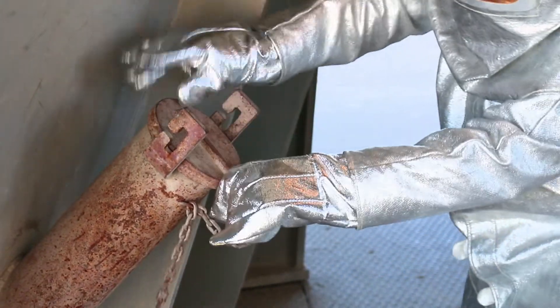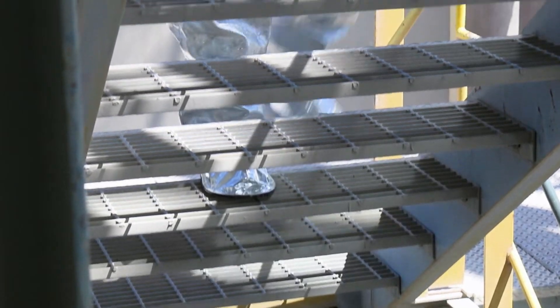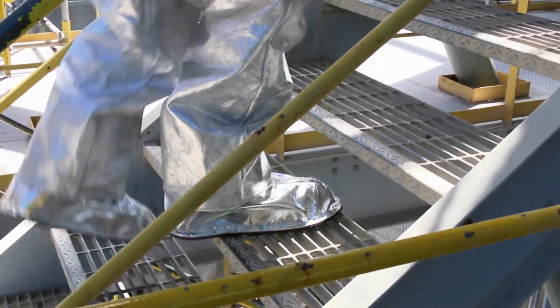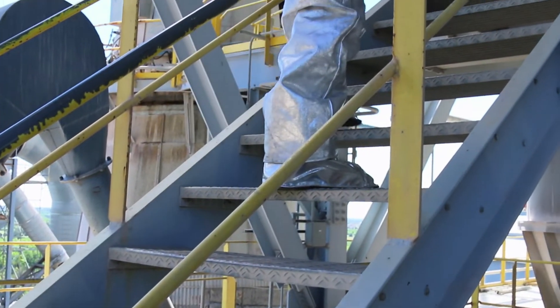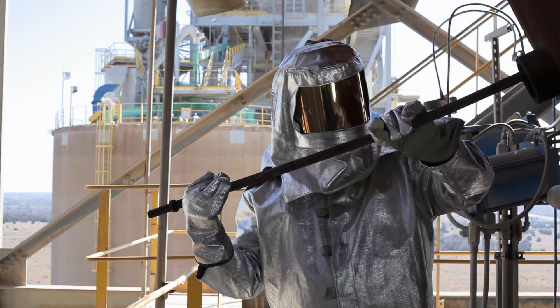The kiln feed is a fine powder that flows like water if discharged. A kiln feed discharge is a very dangerous situation. When working on a plugged vessel, always check for an escape route and which way the wind is blowing. The escape route should always go up and away from the vessel — never down. There should also never be anyone working below a plugged vessel. Employees should be positioned where the wind would be blowing any hot dust away from them. Under no circumstances should you open a hole or port larger than cardox or CO2 size. Use a small 4 to 6 foot poke bar to locate the plug. Air or water should never be used to locate a plug.